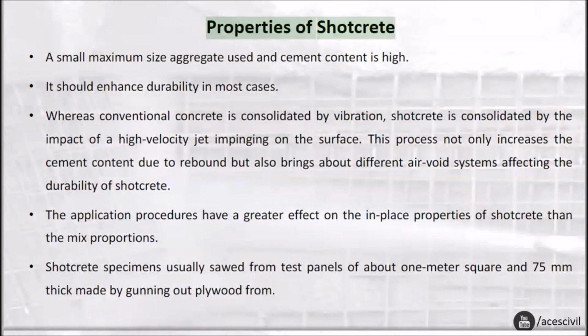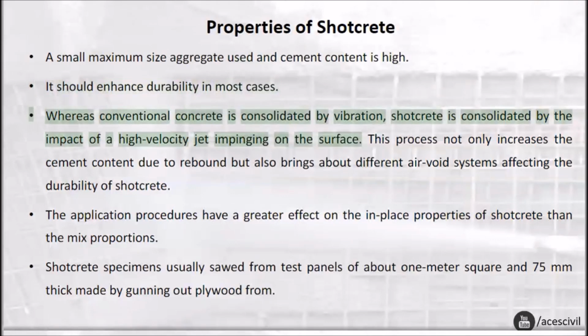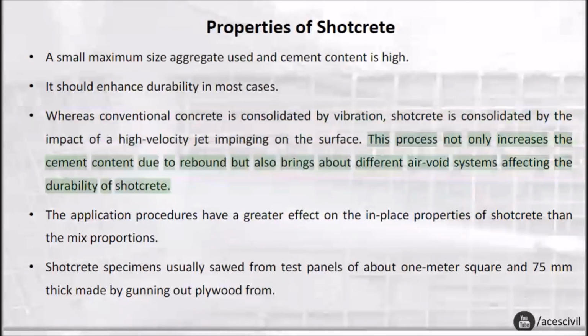Properties of shotcrete. A small maximum size aggregate is used and cement content is high. It should enhance durability in most cases. Whereas conventional concrete is consolidated by vibration, shotcrete is consolidated by the impact of a high-velocity jet impinging on the surface. This process not only increases the cement content due to rebound but also brings about different air void systems affecting the durability of shotcrete.